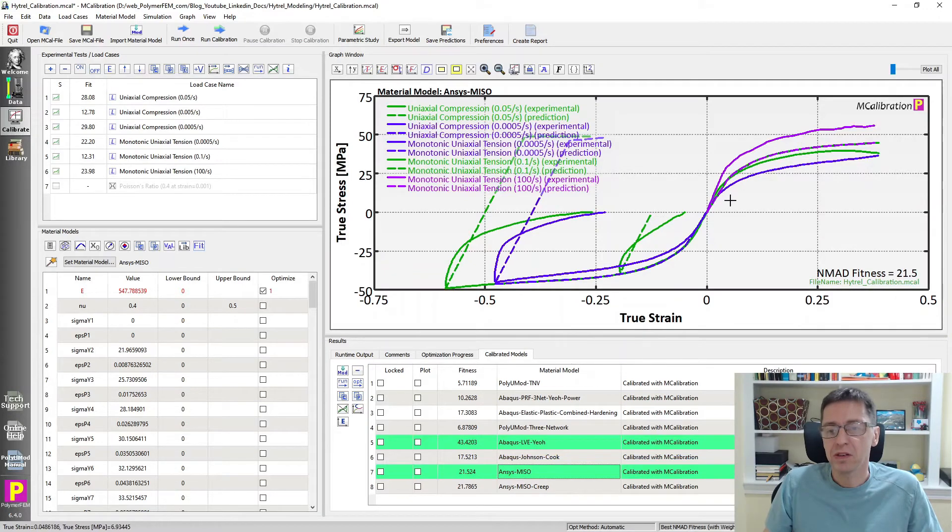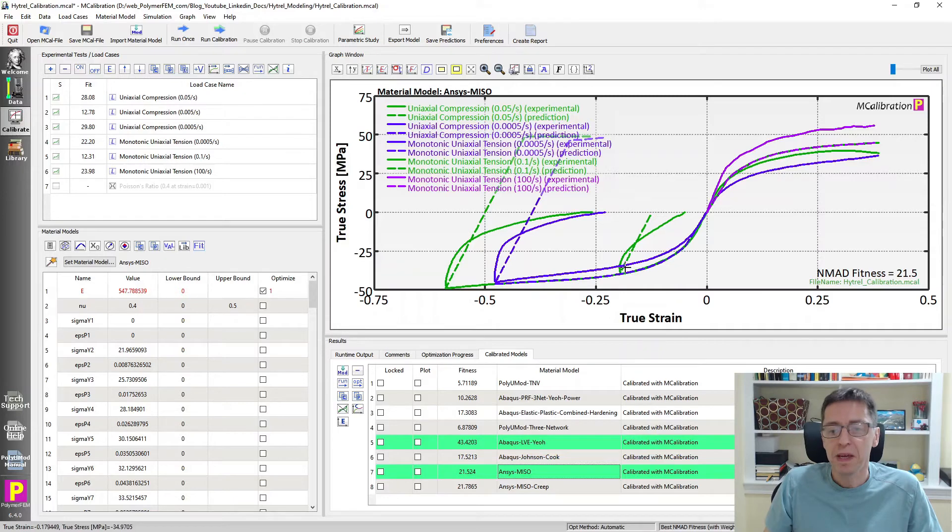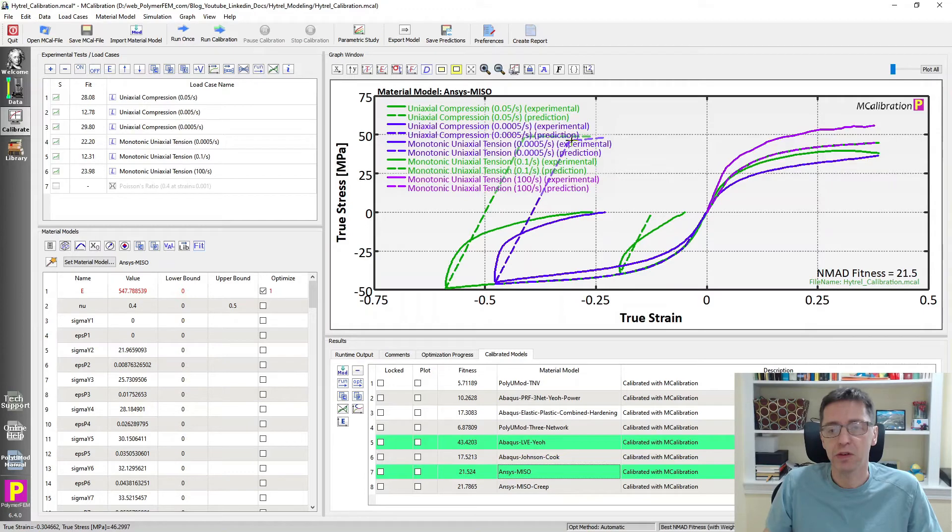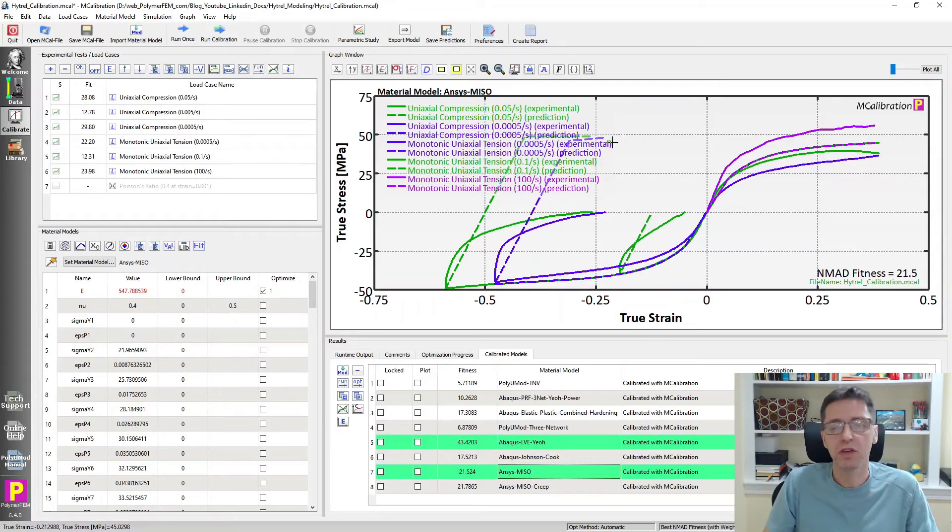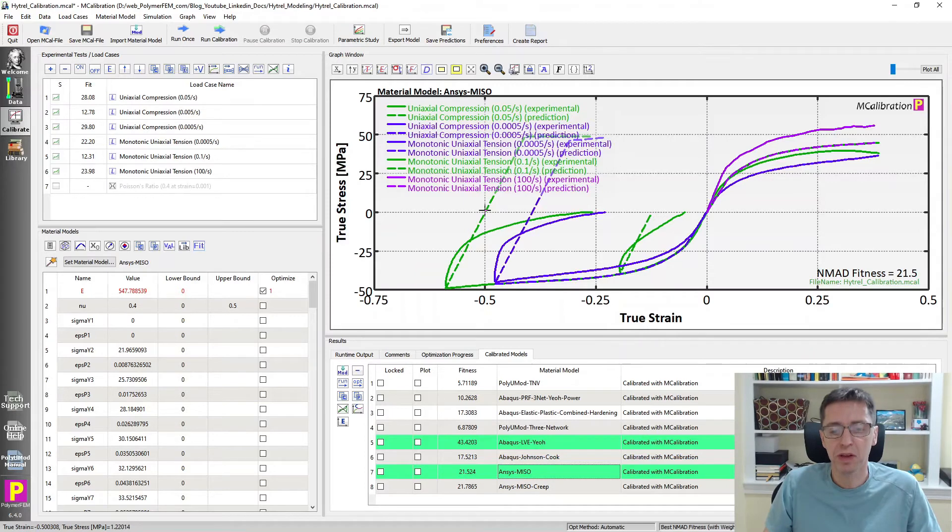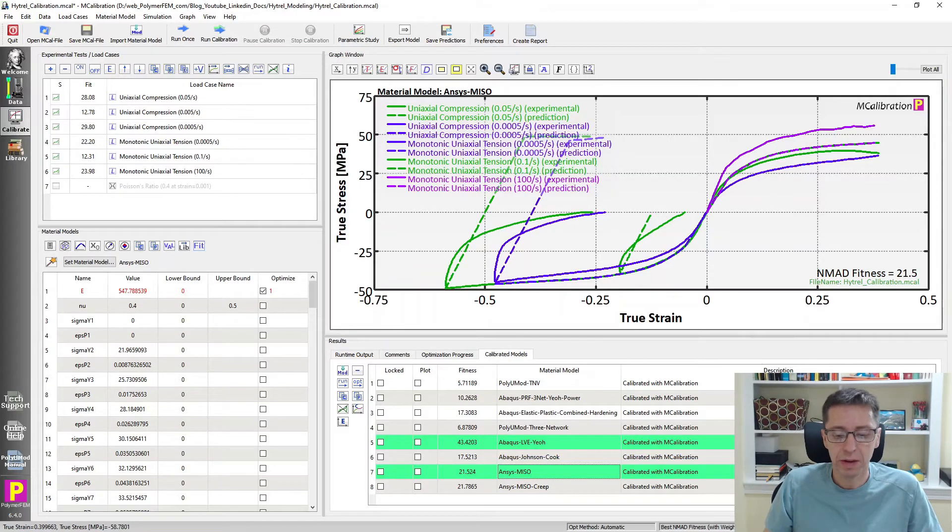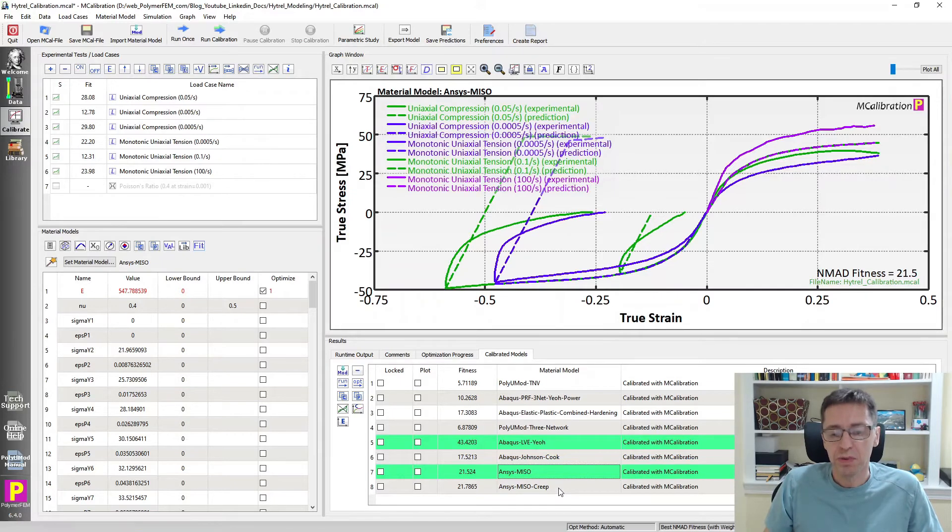In this case, I didn't activate rate dependence to it. But the main problem, I would say, is the unloading is strictly linear until you get reverse plasticity far out here. Not what we see experimentally. It way overestimates the permanent set. The error is about 20%. Not a good choice, really. You can activate a creep to this, and that doesn't really improve the predictions either.